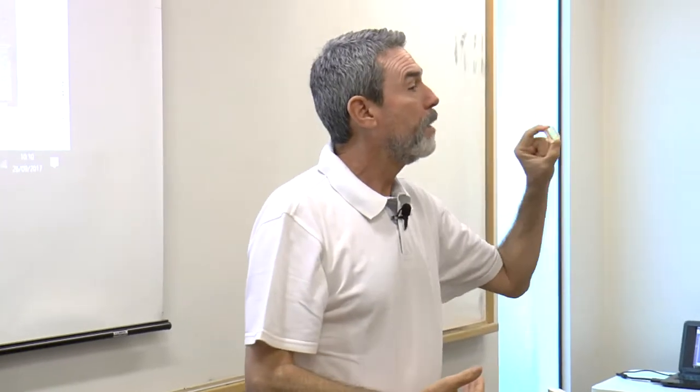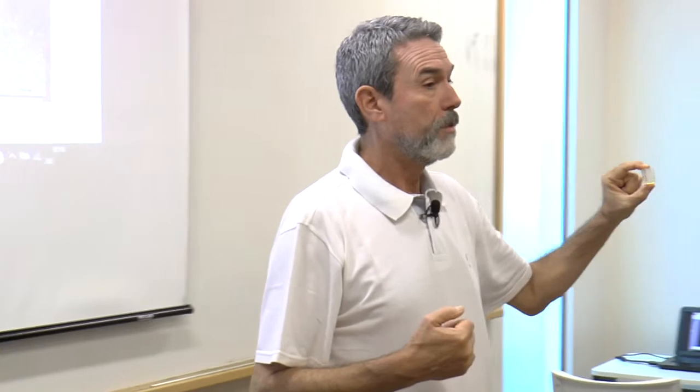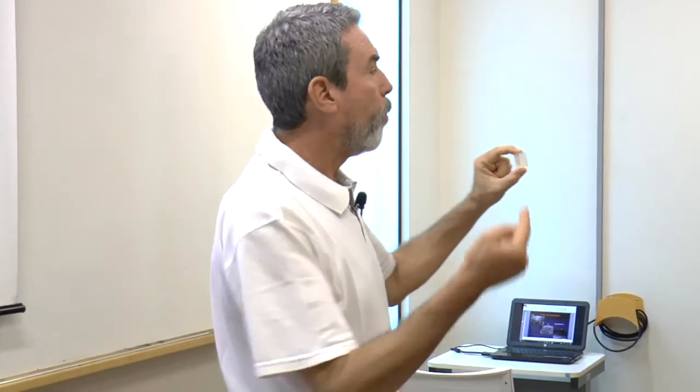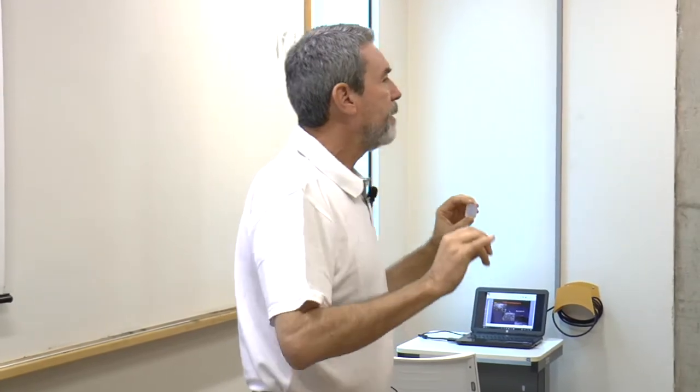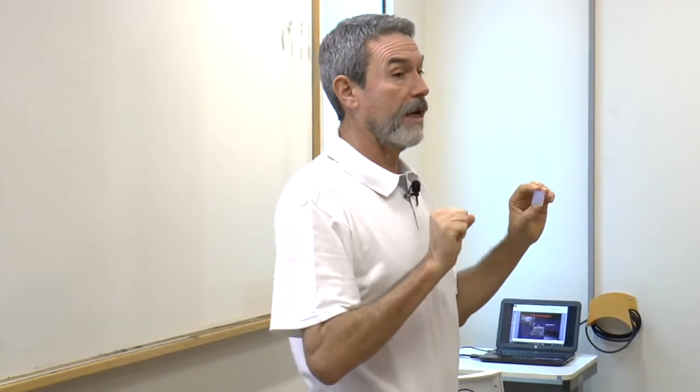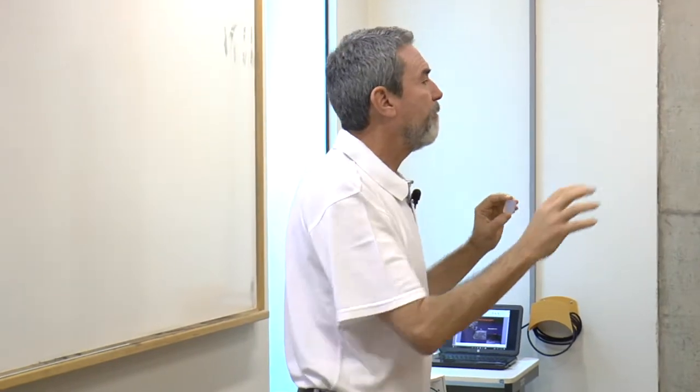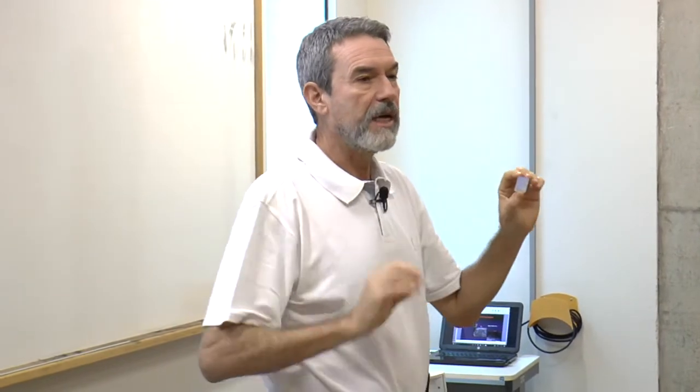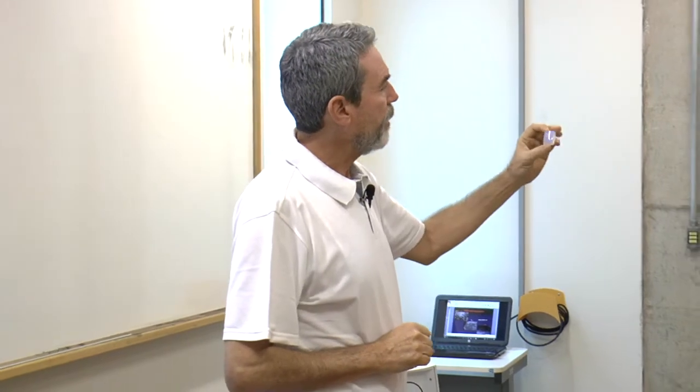It's one glass inside another glass. And this glass has no transition metals or rare earths. So why is it colored? It's colored because these particles have more or less the adequate size just to scatter light. 400, 500 nanometers, this kind of size range. So it's bluish.